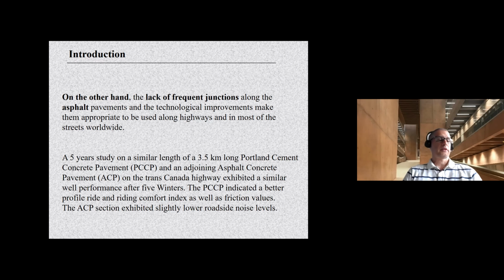We looked at a study that was done on similar conditions, exposed to similar conditions: a 3.5 kilometer long Portland cement concrete pavement and asphalt concrete pavement on the trans Canada highway, which exhibited good performance in both cases after 5 winters in this short period. The concrete indicated a slightly better ride profile and riding comfort index, as well as friction values, while the asphalt section exhibited a slightly lower noise level.